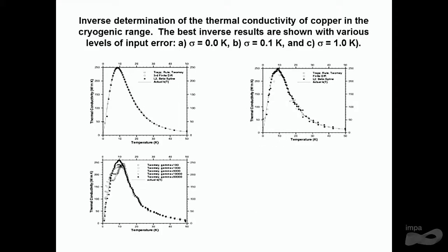Here is an example of actual copper. Copper has highly nonlinear thermal conductivity in an extremely low temperature range. Most of the techniques nowadays are capable only of predicting one single constant value of thermal conductivity, or at most linear variation. This one, as you've seen, can predict a highly nonlinear variation of the thermal conductivity, again with a number of different basis functions, and different levels of the errors in the boundary measurements of the temperature.